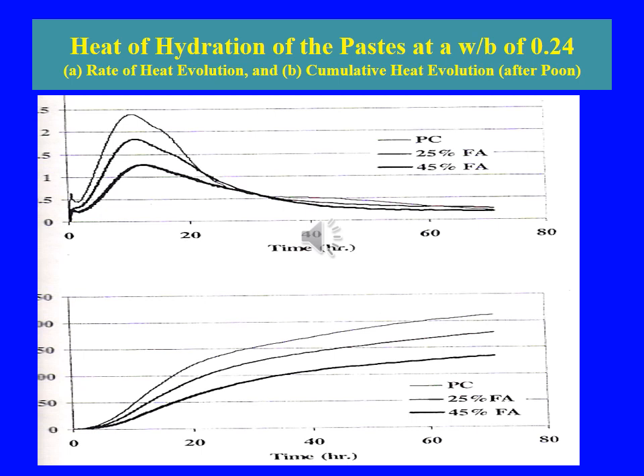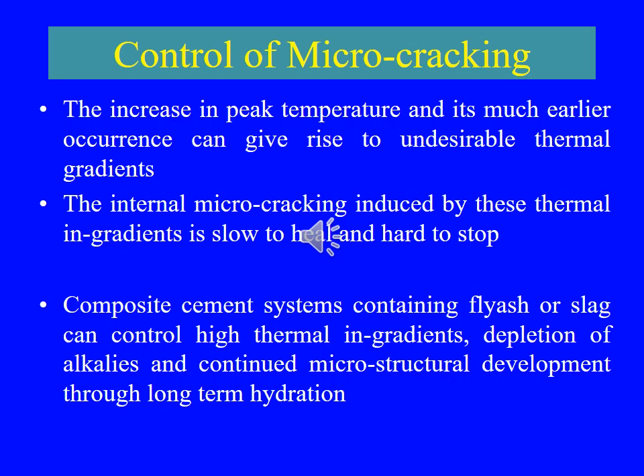As can be seen, with the addition of fly ash, the heat of hydration can be reduced drastically. These two figures illustrate this. Increase in peak temperatures and their much earlier occurrence can give rise to undesirable thermal gradients, and these can create microcracks in the concrete. These microcracks can develop further when loading comes over the structure and turn into wide cracks. These get interconnected and form paths of ingress of moisture or ions in the concrete.